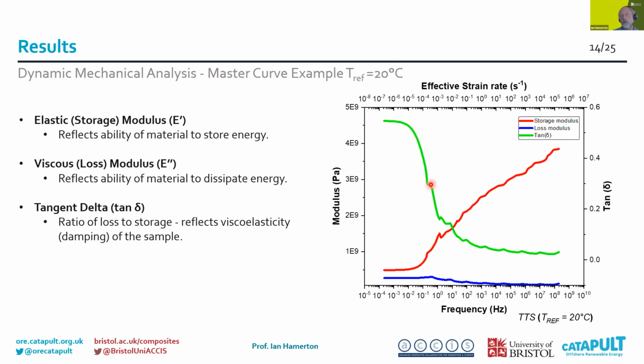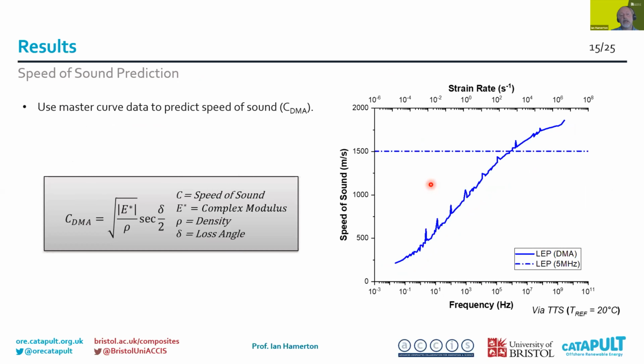And this tells us about how well the material stores energy, how well it dissipates energy, and what its damping characteristics are like. So if we can understand more about its damping characteristics, we can determine whether it's going to be more efficient as a coating for us under these conditions. So this gives us our master curve, and as you can appreciate, if we do a single test using the single probe, we actually find we can measure the speed of sound, but this is, in this case, at 5 megahertz.